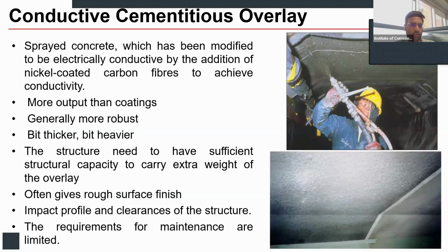Next system is conductive cementitious overlay system. These are mainly sprayed concrete, which become electrically conductive by adding nickel-coated carbon fibers to achieve the conductivity. The typical thickness is about 8 to 12 mm. However, they have more output than the coating systems, generally more robust, but because the thickness is quite high, it becomes thicker and heavier, and the structure should have sufficient capacity to carry this extra weight. Often there is rough surface finish, impacting profile and clearance of the structure. The requirement of maintenance is however limited, and it can increase service life up to 25 years, but they have to be applied through wet spraying technique only.